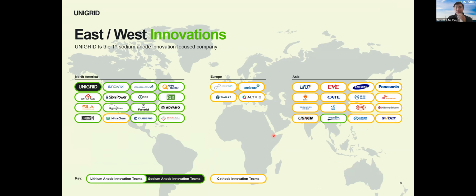When we were doing our competitive analysis, an interesting observation we made was that most of the cathode innovation teams, those you see in orange here, tend to come from Asia or originate from the EU, while most of the anode innovation teams come from North America instead. Which is why we often hear of anode innovation teams like your lithium metal teams, silicon teams, anode-free teams coming from US university spin-offs. It seems like North America is a great place for anode innovation. However, the market dynamics are starting to shift. More and more people are looking towards sodium, which is why we are all here today. And today we are one of the first to enable energy-dense sodium alloy anode innovation, but we can expect more to be adopting this in the near future.